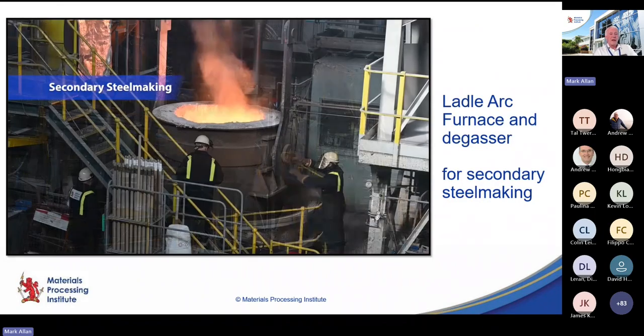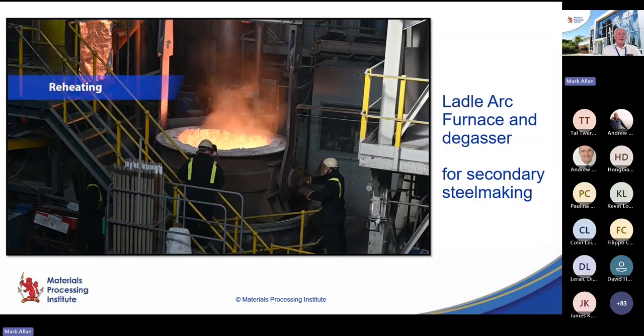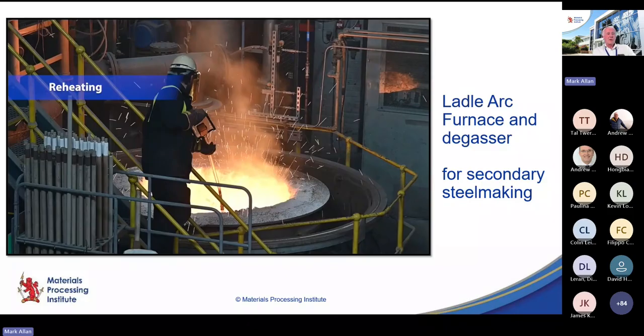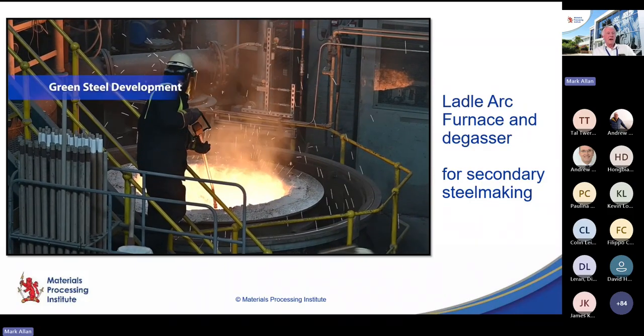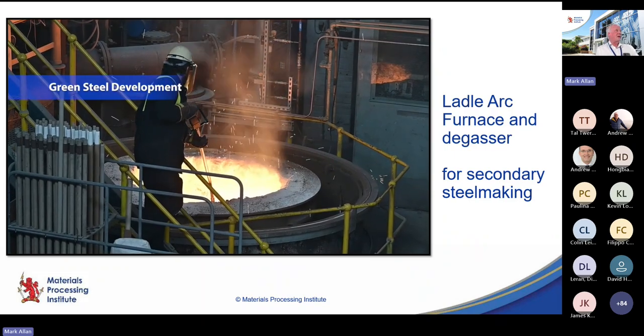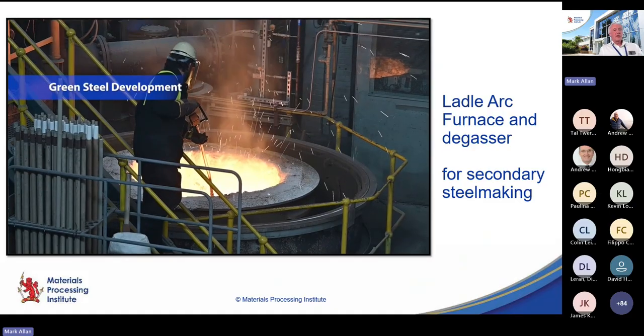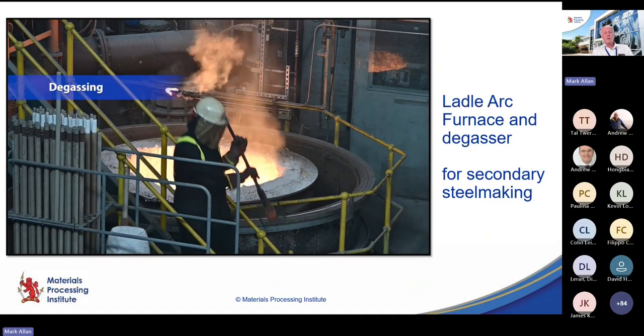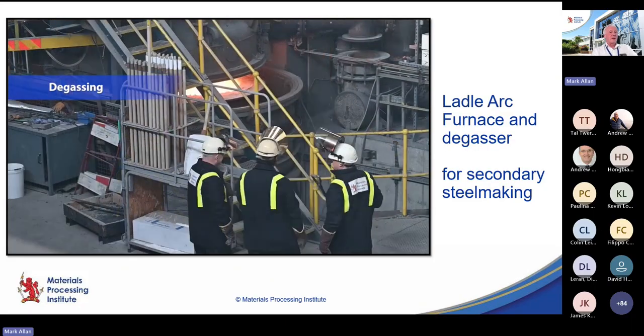So we have a secondary refining capability where the ladle of steel can be then moved into a tank, and in the refining station we have both ladle arc heating capability where we can alloy and stir and refine whilst maintaining temperature. But then when the tank moves under its close-fitting roof, we can then draw a vacuum and carry out vacuum refining activities, which allow us to make almost every steel grade we could be called upon to make, with some reservations over things like ultra low carbon stainless, but most steel grades that we could be called on to make, we can make.